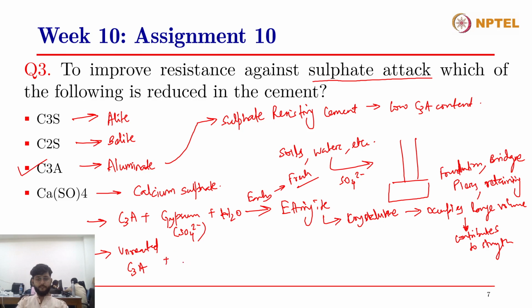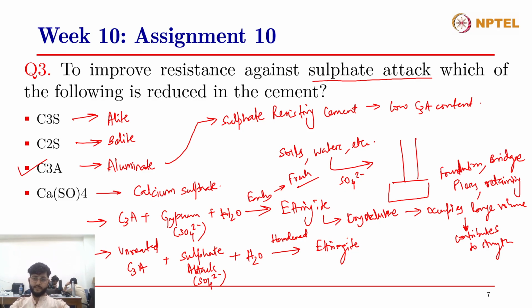inside the cement, and there is a sulfate attack. This unreacted aluminate will react with the sulfate ions coming from any type of attack. It could be magnesium sulfate, sodium sulfate, potassium sulfate, it doesn't matter. The sulfate ions react with this unreacted aluminate and the water present in the pore solution after the concrete has hardened to produce ettringite. Now, the porosity is already reduced. The concrete is not in a plastic state to accommodate any further increase in volume. So, when this crystalline ettringite is formed at a later stage, it doesn't have sufficient space to expand, and therefore it exerts a tensile force inside the concrete, causing cracking.